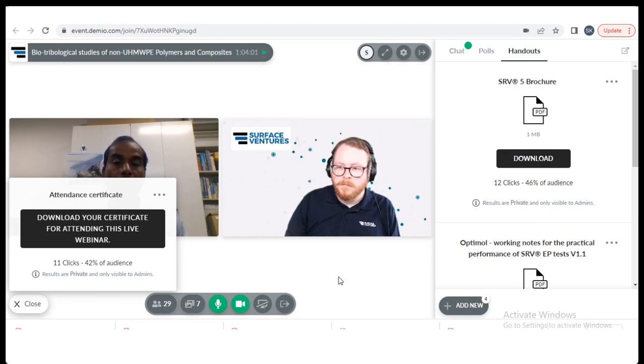Of course, in a normal pin-on-disc machine, you cannot see the mixed lubrication acting. What you can do is perhaps make one side of it transparent, and then do some imaging from the back side, and you can show that there is some formation of mixed lubrication. Theoretically, you can prove it if you know the shear stress and the velocity, and you conduct the test at different velocities, you can show that there is a mixed lubrication condition here.